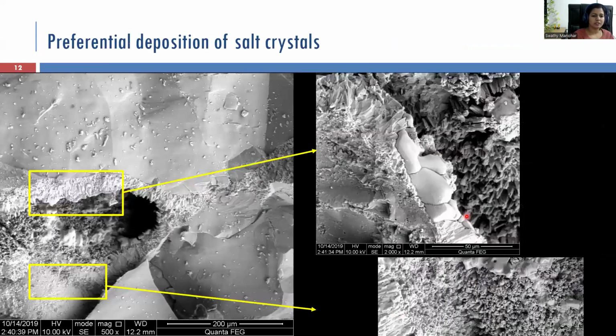Another interesting observation from this stone was that there are larger porous magnesium calcite lining, and there were also smaller porous calcite. But when we looked for the precipitation of sodium chloride crystals, we saw that the crystals were only in the larger magnesium calcite pores, not in the smaller calcite pores at the bottom. The reason is something called preferential deposition of salt precipitation.